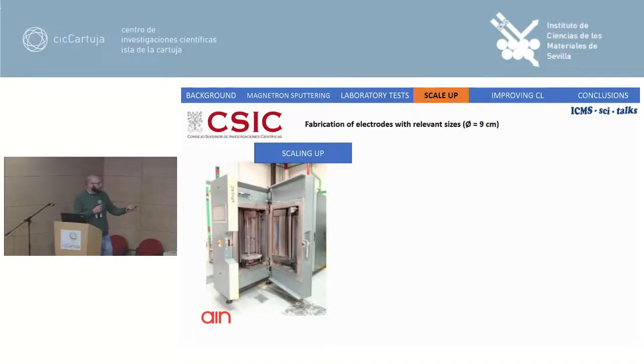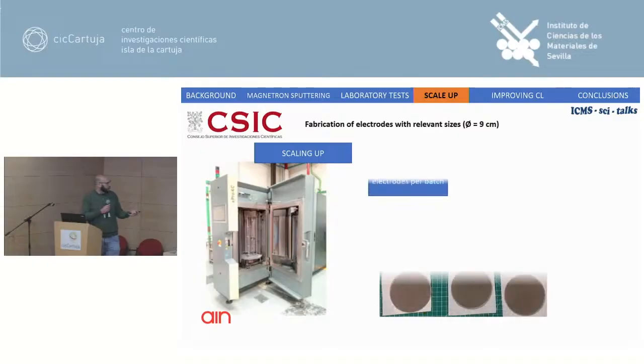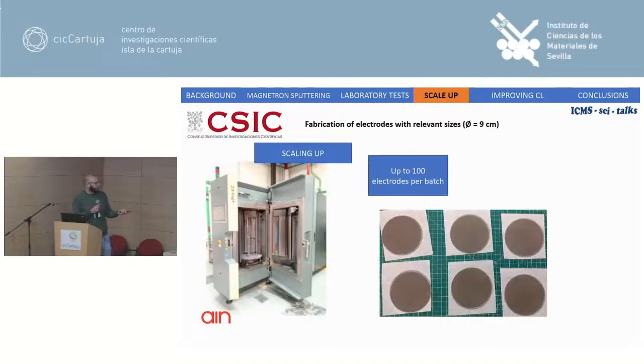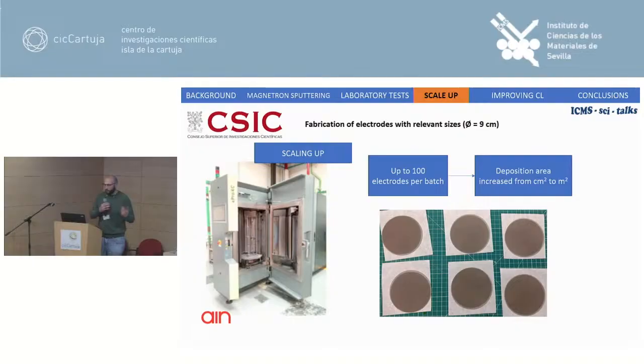To do this, we chose an industrial magnetron sputtering chamber, like the one shown here, that gives us the possibility to obtain electrodes of bigger area. This is an electrode of 9 centimeters of diameter, which translates to 64 square centimeters of area. Remember that the previous one was 5 square centimeters, so we have multiplied the area by 12 or 13 times, and we can obtain up to 100 electrodes per batch. So we are increasing by orders of magnitude the capability for the deposition of catalysts, from the square centimeter to the square meter.